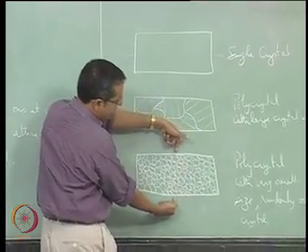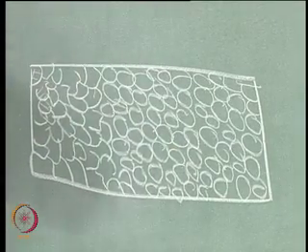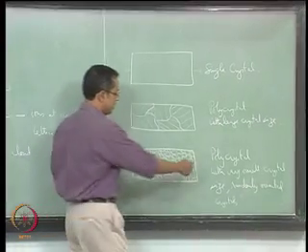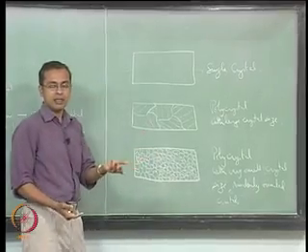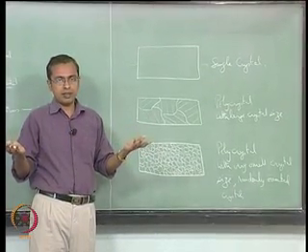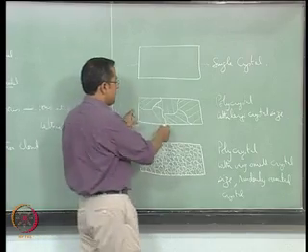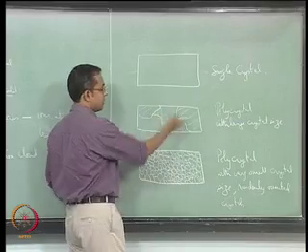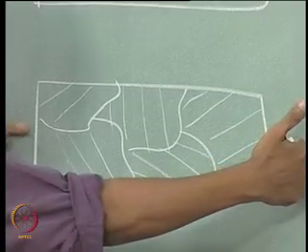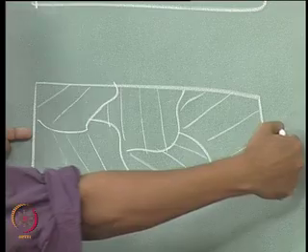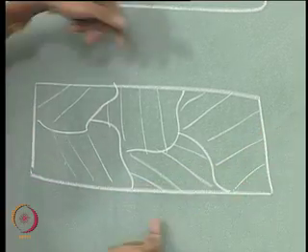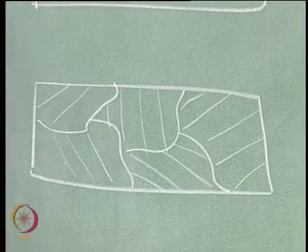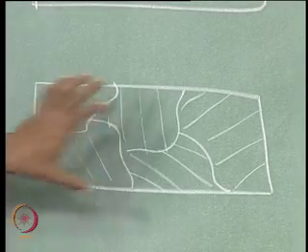If you make the same measurement this way, you will get, and you normalize it for the size of the sample, okay. So let's say conductivity or resistivity, not resistance, resistivity, if you measure it this way or this way, you shouldn't see a big difference, because the crystals are all randomly oriented and there are many of them. On this sample, even if it were randomly oriented, since the crystal size is large and you only have 5 crystals from here to here, when you take a measurement this way, on average there is greater orientation in a particular direction along this way and greater orientation in some other direction along this way, okay.